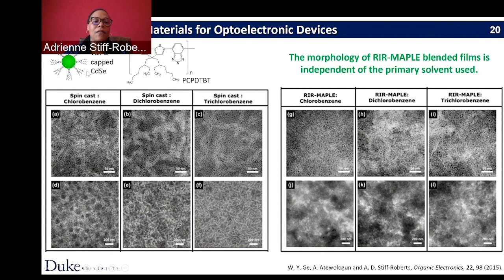So here, these are showing nanocomposites of these nanoparticles in a polymer, deposited by spin casting using 3 different solvents. As you can see, the distribution of these nanoparticles within the polymer matrix varies as a function of the solvent that you use, just based on how that solvent evaporates. When you look at the same 3 solvent systems deposited using RIR-MAPLE, you get the same sort of random, homogeneously distributed nanocomposite of these nanoparticles in the polymer. While it's not an ordered film, it is homogeneous, and it has blending of these 2 components on the nanoscale, which is, again, difficult to achieve with solution processing.